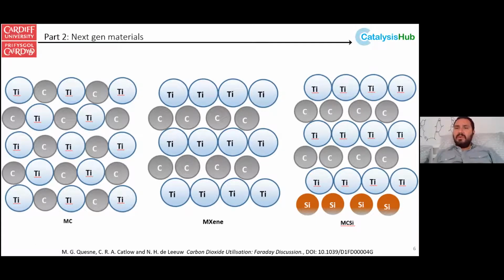When we had a look at this, we thought it's interesting to see the similarities between this kind of material and two-dimensional silicon carbides, where one of the carbon layers is substituted for an interstitial layer of silicon. These materials are well known to exhibit quite a strong preference for the basal 0001 plane with the metal terminated surface, which is quite nice for us because these things are also formed through coking, and they're very stable. They're very stable and thermostable ceramics. So we thought, okay, what are the properties that change with the silicon carbides versus the MXenes, as these would be quite an interesting target that hasn't had the same kind of focus as the MXenes have.